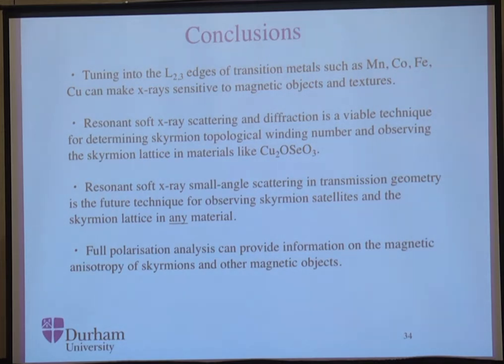If you go onto the absorption edge, close to the absorption edge, as you go through that absorption edge, the sensitivity to orbital and spin will change. So by doing those measurements at a number of energies very close, generally the greater sensitivity to magnetism will be almost on the top of that resonance. The orbital ordering, you tend to get greater sensitivity if you back off a few fractions of an eV. It can vary from one element to another, but manganese, iron, cobalt, they're all roughly the same. So yes, I think that is possible in the future.